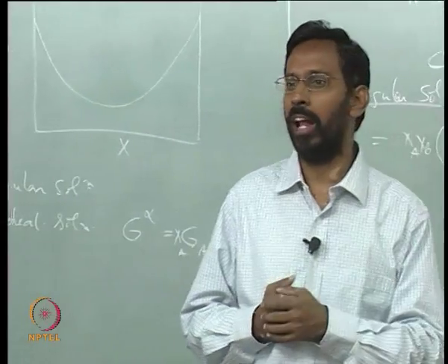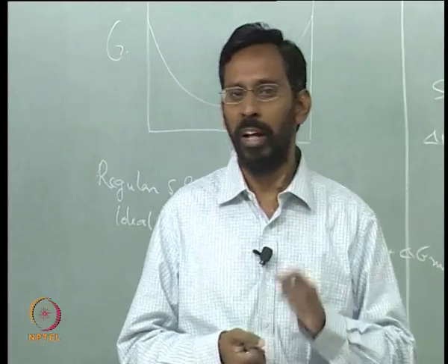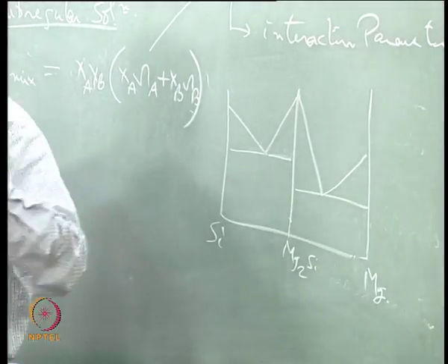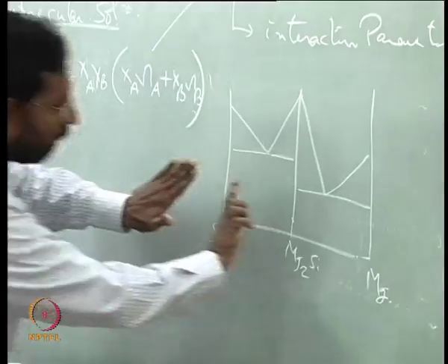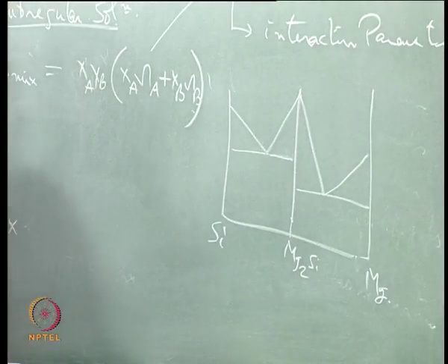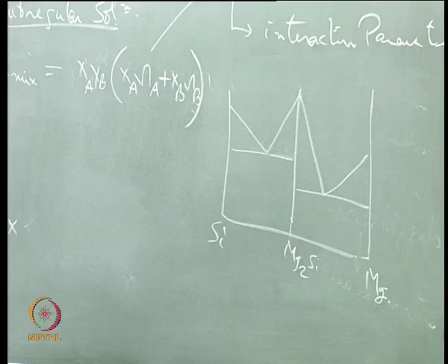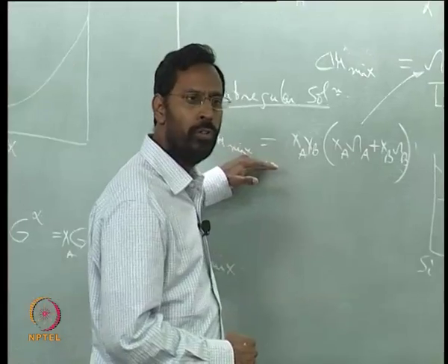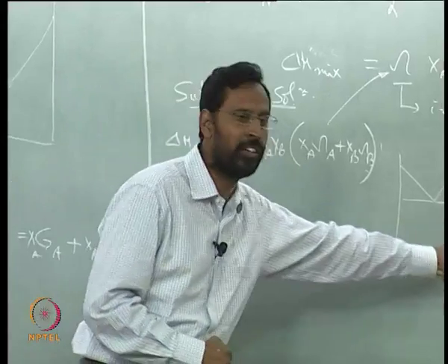People have classified them into a variety of types of compounds: electron compounds, size factor compounds. Let us not go into details of them, but there is a possibility that the interactions can be specific to certain compositions. And if I come to either this side or this side of the Mg2Si composition, that interaction vanishes. That means the free energy is strongly negative at this composition, and this is the reason why people had to use some other models beyond the subregular, because subregular cannot account for this.